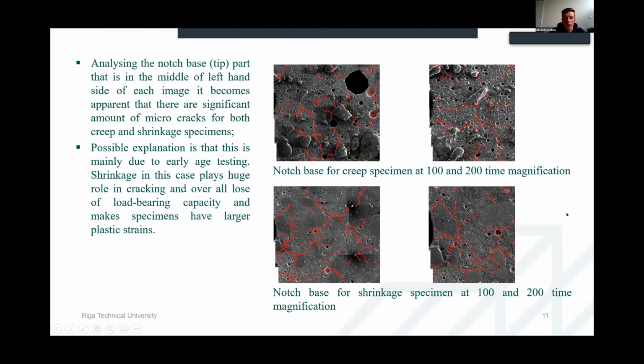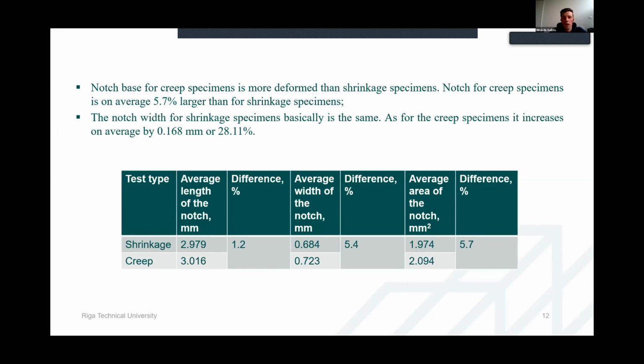So further analyzing the polished sections of the tension specimens, we can see here, this is the notch base, or the beginning of the notch of the compact tension specimen, that for them there is a significant amount of microcracks, and most of these microcracks go from one pore to another, and then make a kind of significant mesh in there. And it's not only for the ones that were tested for creep, but also the ones for the shrinkage. So this leads to thinking that because of the early age testing, shrinkage plays a huge role here in the microcrack development, and therefore the loss of tensile strength.